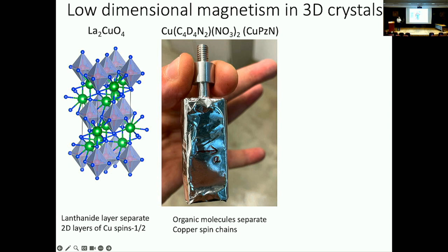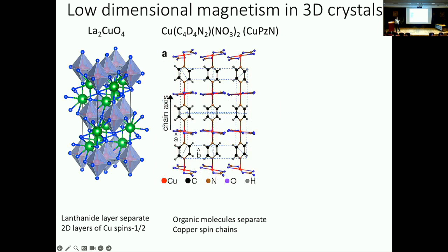Okay, so here's an example of a one-dimensional material. We call it a coordination polymer magnetic material, and you've got someone holding it here. It's in the form that we use it for neutron scattering experiments. So inside this package are many, many crystals that we grew, and then we've aligned them with respect to each other to an accuracy of a couple of degrees. A little bit of glue is holding them in place. I'm not showing that, but in our minds, all of this boils down to a macroscopic assembly of lines of spin, so a one-dimensional magnetic material is in there. And we know exactly how it's oriented.